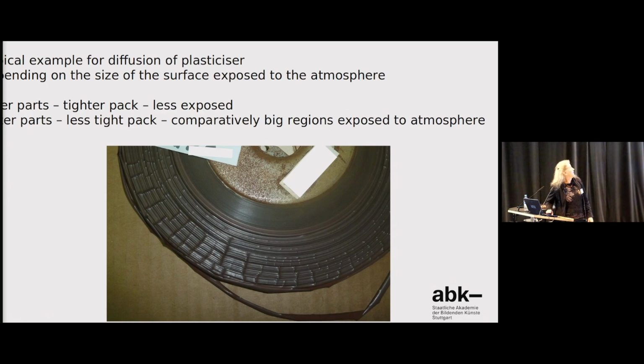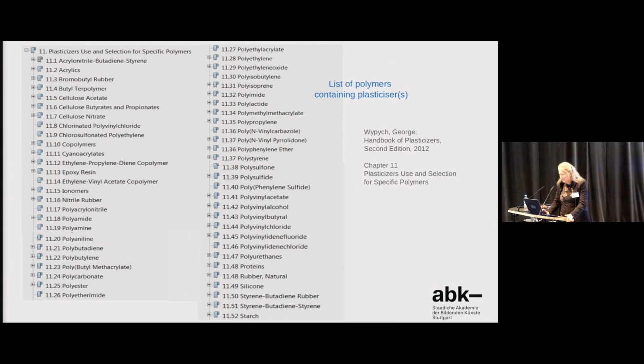And here, a wonderful example for diffusion of plasticizer depending on the size of the surface exposed to the atmosphere. Here we say that the inner part maybe never has been played and never has been exposed to the atmosphere because it was tightly packed, so there is no shrinkage, but in the outer layers you have the shrinkage, which is a physical factor. The list of polymers containing plasticizers is very, very long and can be seen in the Handbook of Plasticizers from George Wypych. I think it's a Polish name.